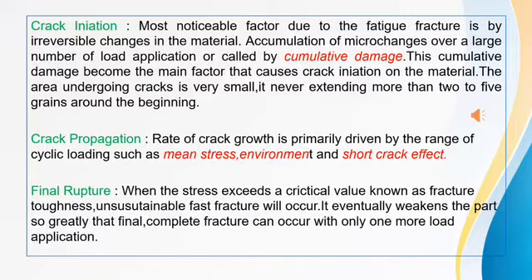When the stress exceeds a critical value known as fracture toughness, unsustainable fast fracture will occur. The final rupture or final failure can be ductile, depending on the material, thickness, temperature, and the applied stress. This stage will happen suddenly, and the fatigue fracture surface of the broken component is typically smooth and shows no evidence of plastic deformation.